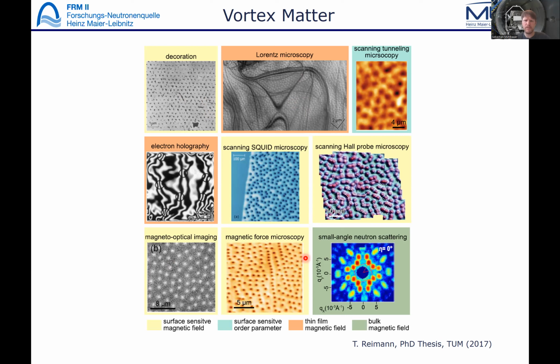And the color code behind these images represents what the measurement technique is sensitive to. What we see here is small angle neutron scattering, which in a way sticks out in that we are sensitive to the bulk of the superconducting vortex lattice. So we're not only looking at the surface. Most of these techniques only look at the surface of the samples, but with small angle neutron scattering, we are really able to look at the bulk of such a superconducting vortex lattice. And that's why SANS is very useful to do vortex lattice crystallography. And this is exactly what Emma has been doing.